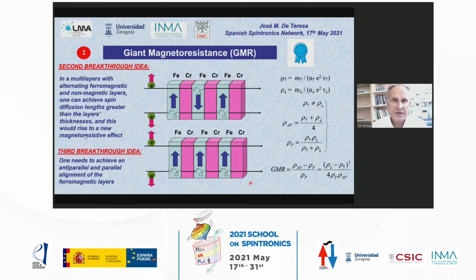So we have the first ingredient, but no application from the 30s until the 80s. In the 80s, there were new thin film growth machines, molecular beam epitaxy and sputtering machines, that allowed preparing materials with a very good control of the thickness and the roughness. And then it was possible to grow multilayers of ferromagnetic and non-magnetic materials with very clean interfaces. So if we are able to create one of these multilayers in which we have materials with spin diffusion lengths greater than the layer thickness, then we will observe a new phenomenon.